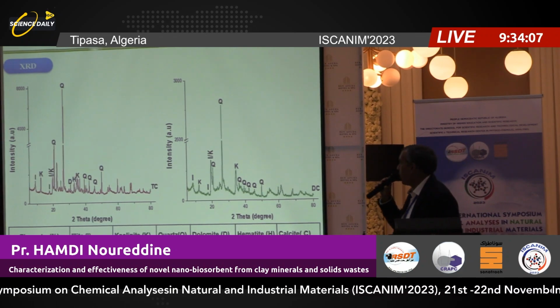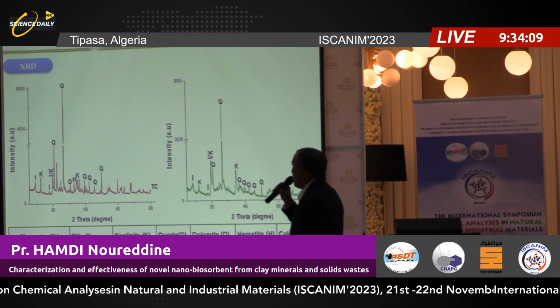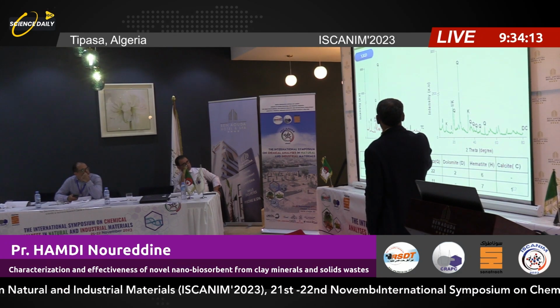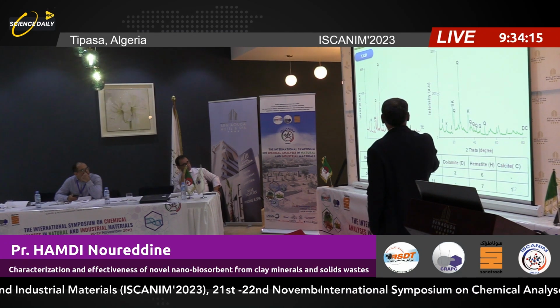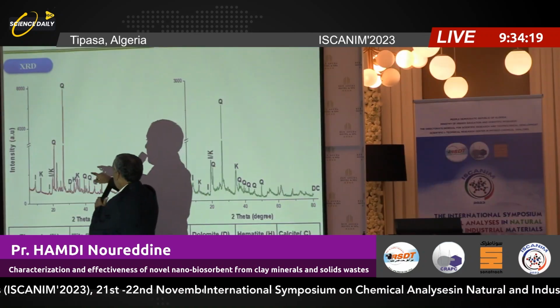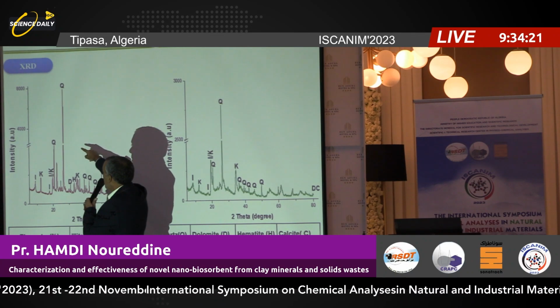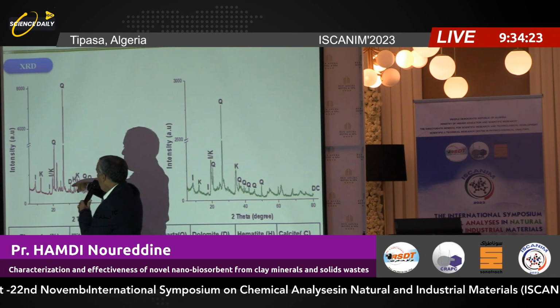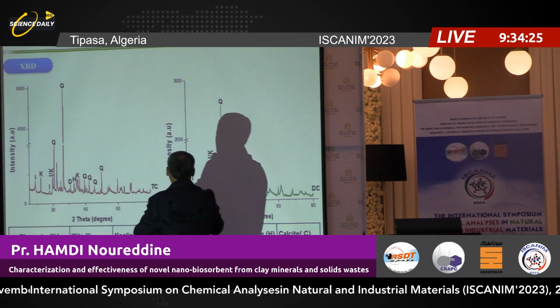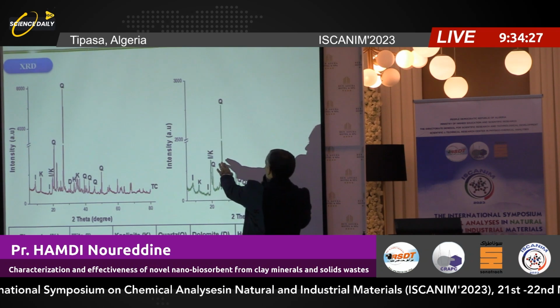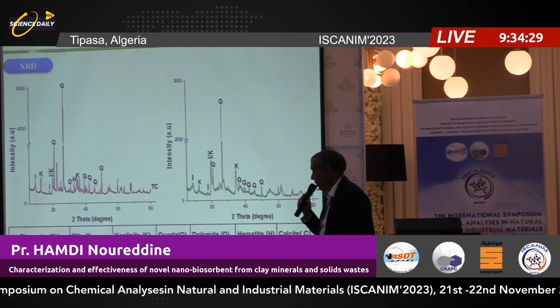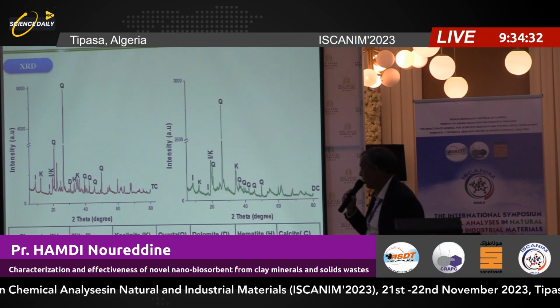We used here two clays. We have the same composition, halloysite and kaolinitic clay, with impurities in the first case. In the case of the Tejra clay, the impurities are quartz, dolomite, and hematite. And in the second one, we found only quartz. The percentages are in the table.